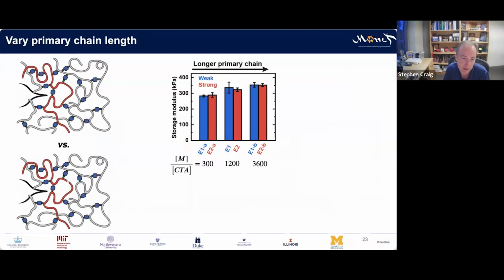experimental evidence for it. Because what he did was he took advantage of this controlled radical polymerization and made networks in which he changed the length of the gray strands. And I've highlighted one of them in red here just to accentuate it, right? So some networks he makes with very long strands and others with shorter strands, which you could think of as what you would have gotten if you just went through up here and snipped a few of those strands randomly throughout the network, okay?